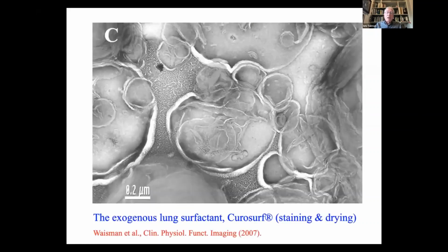In the older days, people used what we call staining and drying, and people still do it. One used to take the dispersion of your liposomes or EVs, add a stain, typically a salt or acid of a very heavy atom, and then dry it. And in this case, where we look at liposomes that originate from the lung surfactant, we see that the preservation of the structure is really quite bad. We do see that there are some balloon-like structures, but we can say very little about the membrane, for instance.